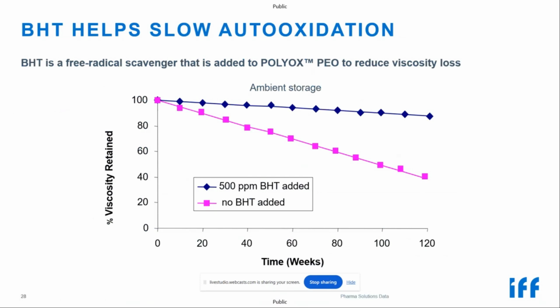We add BHT to help slow auto-oxidation. BHT is a free radical scavenger that is added to every batch of POLYOX polyethylene oxide. This is N80 data looking at how the BHT stabilizes the viscosity over time. The blue line is showing a batch of PEO where 500 ppm BHT was added and then put into storage. The pink is showing where no BHT was added and then put into ambient storage. You can see the drastic difference: with no BHT, the viscosity loss is much faster over the same time as with the 500 ppm BHT. We add BHT to help stabilize the product.